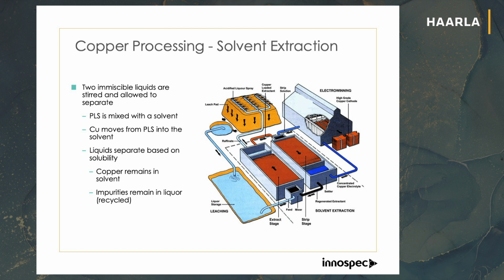In the solvent extraction process, you're looking to get as high a concentration of the pregnant leach solution in that first separation, and then going into the second solvent extraction process, where you are flipping the solubility between the solvent and the aqueous layer, and changing that back to go into the electrowinning process. Anything that interferes with that is going to reduce the efficiency of your process, and that can happen.